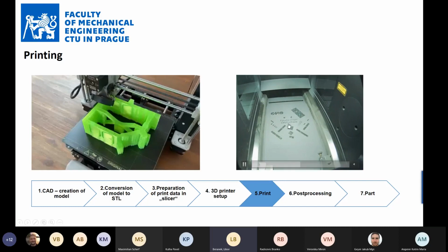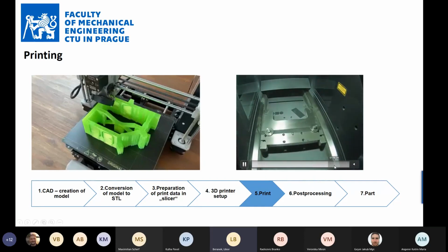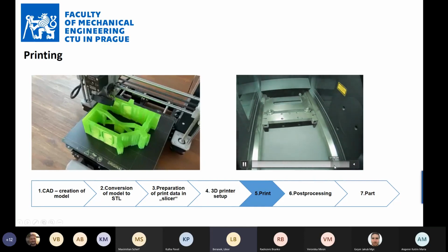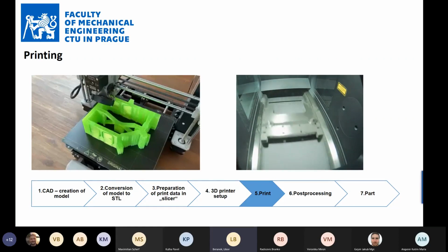Of course, the other way is that you can preheat the whole building chamber. For example, we don't have this option, but when you have EBM machines, electron beam melting, you can preheat the powder bed up to 1000 degrees Celsius. And thus you can limit the deformations caused by thermal effects. So we don't have the option to heat the powder bed so high, so we need to at least distribute the heat equally. Now you can see the so-called recoater.